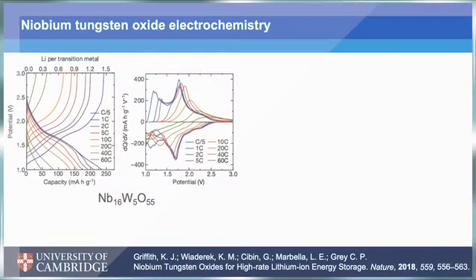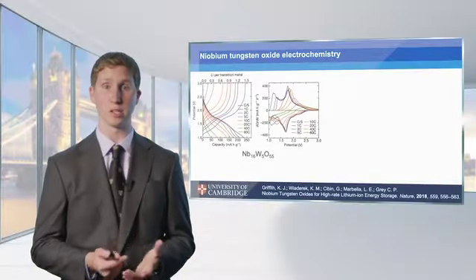And so to jump into that electrochemistry then, we're looking here at the crystallographic shear structure. On the left, there's a plot of the discharge and charge curves and a differential plot next to that on the right, where we can try and envision where this charge is being stored. So we're in the range of mostly between 1 and 2 volts. And the average voltage of these materials is actually almost identical to LTO, around 1.55, 1.6 volts versus lithium.